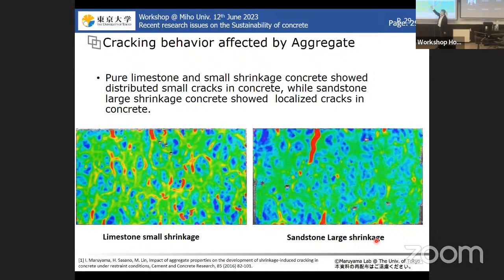But the limestone itself is not shrinkable, and also the bond between the aggregate and the paste is strong. In this case, once the crack develops but stops at a certain depth, then due to the lesser crack opening, we see additional cracks here, here, and here. So with the unshrinkable property and the good quality of the ITZ, the cracks are distributed, something like this. But in the case of the shrinkable aggregate and the weaker bond between the aggregate and paste, we see the cracks develop further, and visible cracks are made in this case.